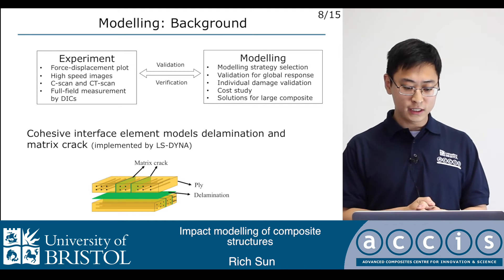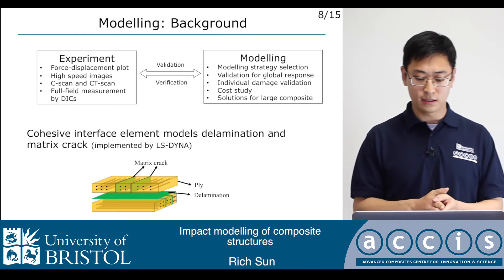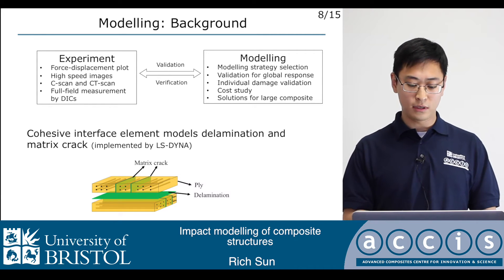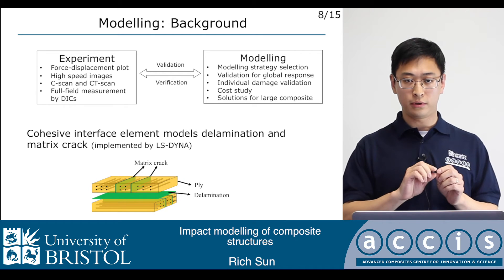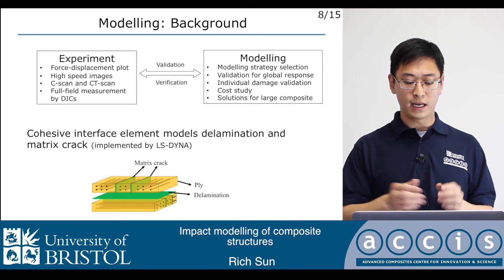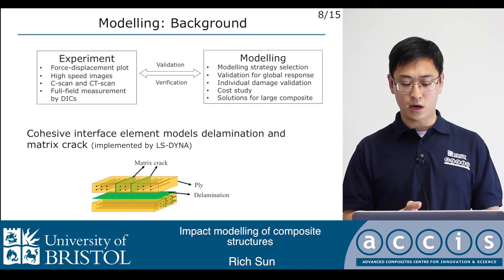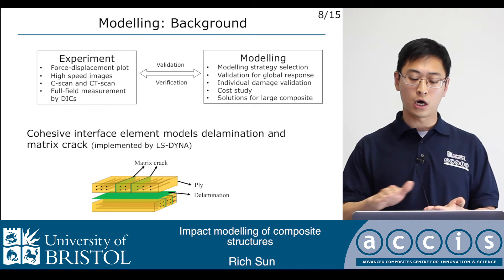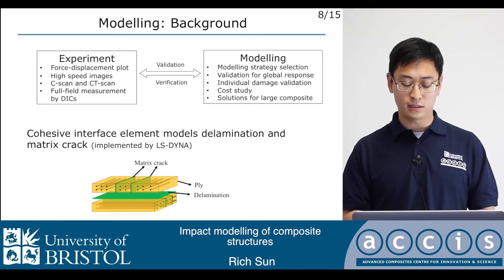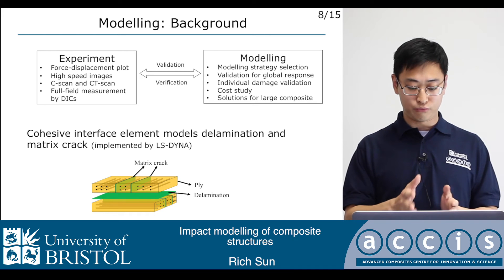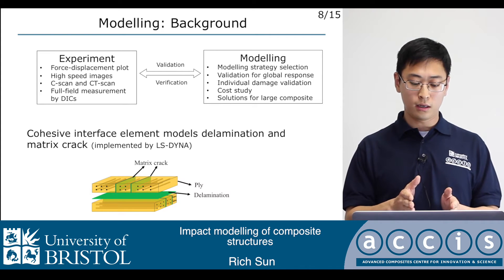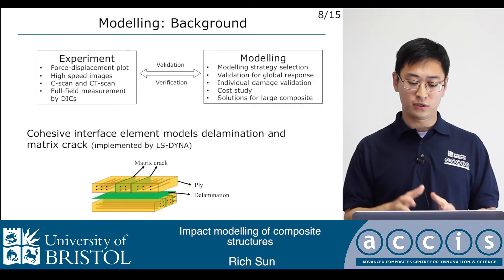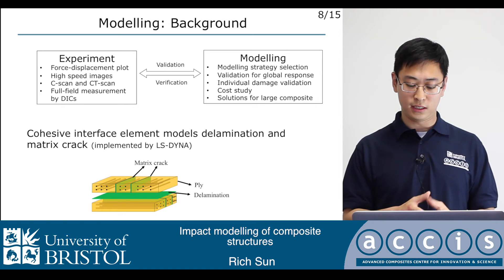We use cohesive interface elements implemented in the solver to simulate matrix crack and delamination. Multiple strips of interface elements are placed at the ply level to simulate matrix cracks, and a thin layer of interface elements between plies of different orientation to simulate delamination. With this approach, matrix cracks physically interact with delamination, and we expect to see results similar to those observed in the CT-scan.